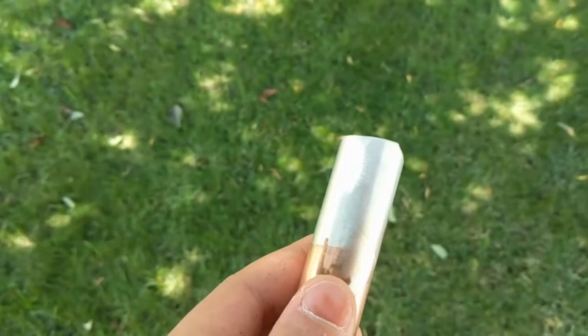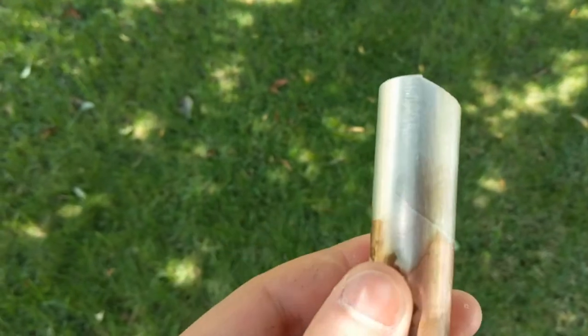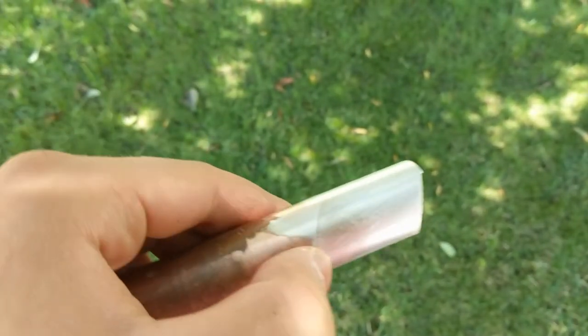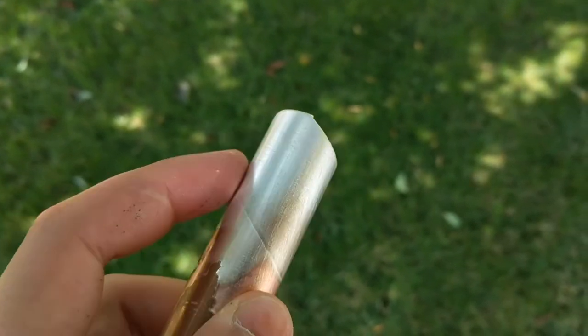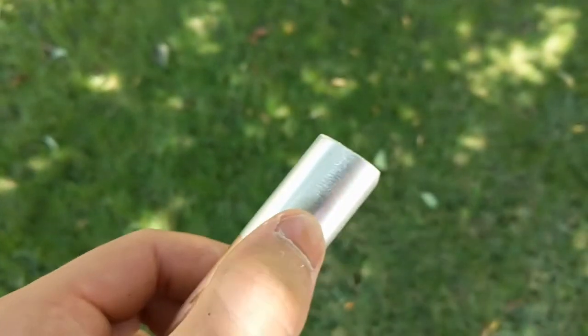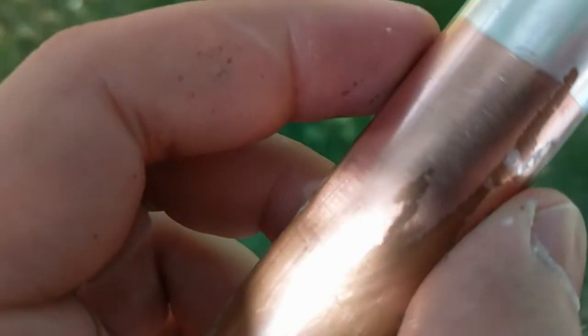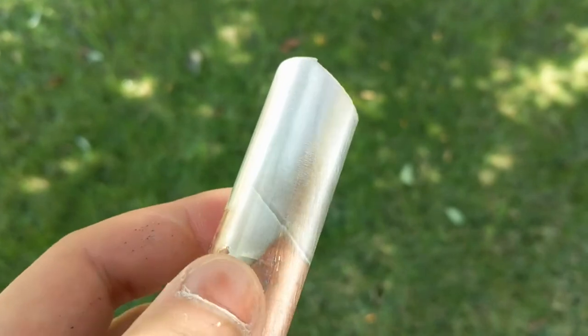Today's the next day, and as you can see the outer coating it's left is a very nice silver color. This area I had immersed initially for about 30 seconds and you can see the silver color isn't quite as intense — it's a bit darker. The rest, which I turned around, has gotten a nice thicker layer. I've given this a scrub with a classic kitchen dish scrubber to see if it was resistant, as it also had a strange white coating, and it does withstand those scratches.